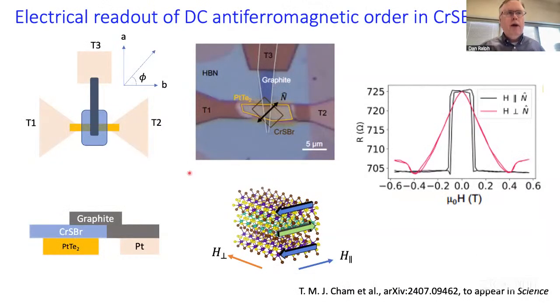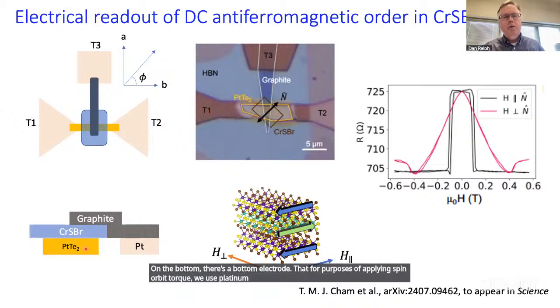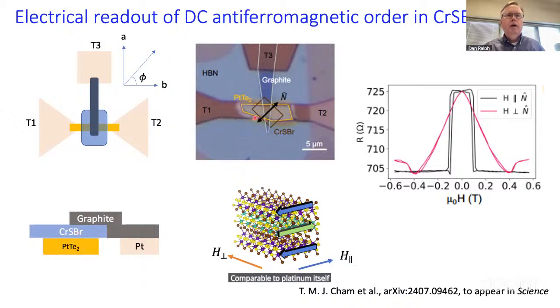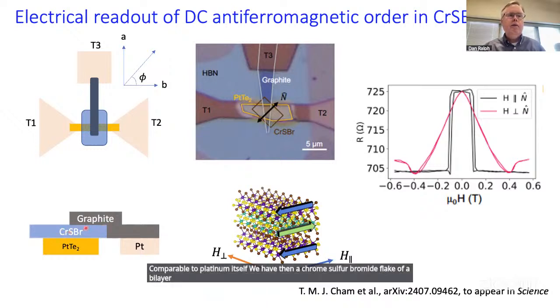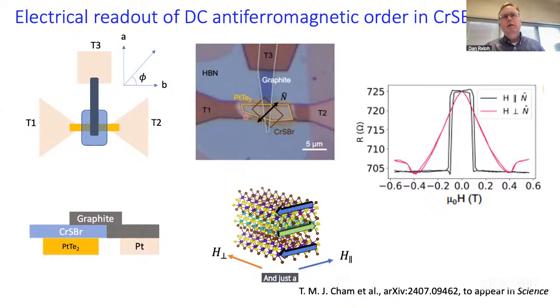Okay, so to try to do the electrical readout on smaller scale devices, this is the nature of the devices we'll look at. These are three-terminal tunnel junctions. On the bottom, there's a bottom electrode that, for purposes of applying spin orbit torque, we make from platinum telluride, which has a large spin Hall conductivity comparable to platinum itself. We then have a bilayer chrome sulfur bromide flake on top of that, and just a graphite top contact. So we can pass current underneath the device, apply spin orbit torque, and measure the tunneling current going through the device, and measure the tunnel magnetoresistance.